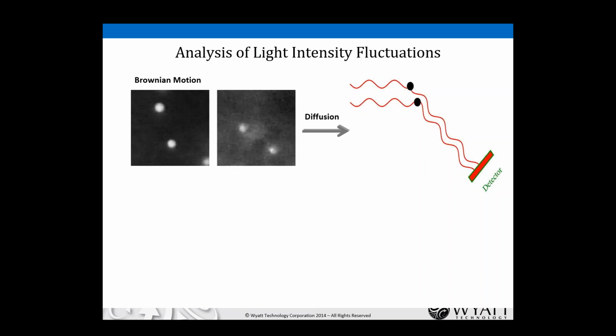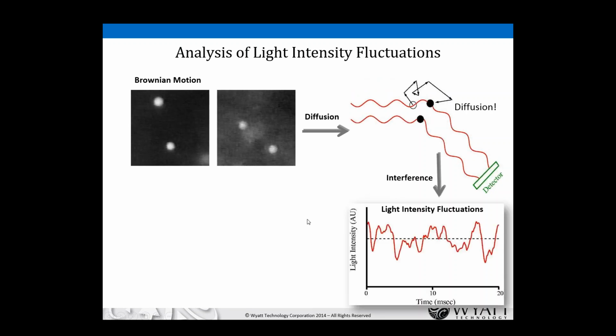And depending on the distance between those particles and also on the angle at which the detector is placed, those two waves might arrive at the detector in phase, in which case they interfere constructively and you'll have a higher light scattering signal. Or if the particles shift a little bit in position, they might arrive out of phase at the detector, in which case you have destructive interference, and that will lead to a lower light scattering signal on the detector. So as these particles are jittering around in solution due to Brownian motion, the phases are jittering around too, and you'll see these rapid intensity fluctuations in the light scattering signal that look kind of like this.